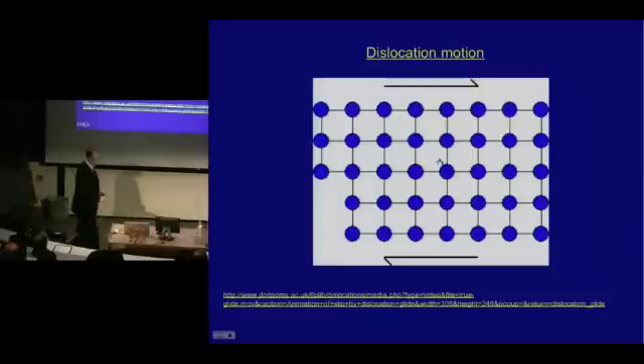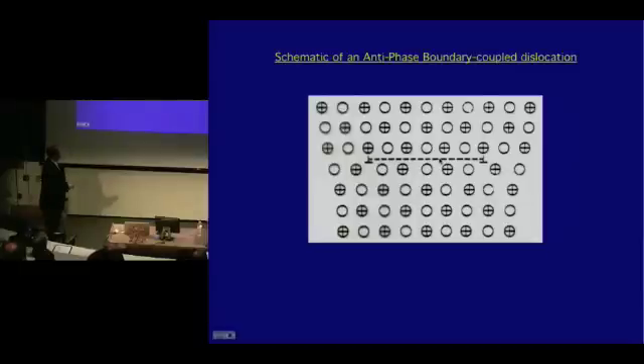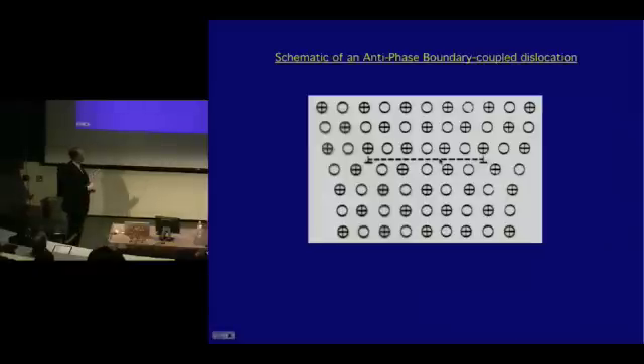In intermetallic compounds, such as iron and aluminum, things are a little bit more complicated. So this is just a 2D section here of a hypothetical intermetallic compound. Two types of atoms, an open circle atom and a closed circle atom. And you can see we've got a perfect lattice here. And if you put one of those little dislocations in here with an extra half plane, what that does is it messes up the lattice so that now you have the wrong type of atoms next to each other. So in order to not produce this continuous plane as the dislocation moves through here of wrong neighbours, you actually have to put another dislocation in there. And it's joined to the original dislocation by what's called an antiphase boundary, which is right here. And we'll see some of those in a bit. And they turn out to be quite important in this material.